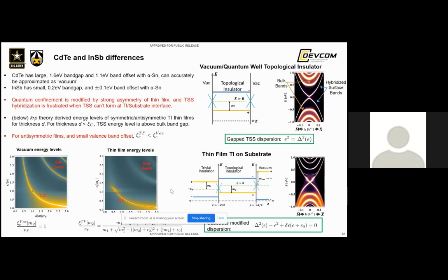Good question. We have thought about that. It's just experimentally very difficult to realize. Alpha tin is quite tricky to grow or to deposit on most materials. It doesn't like too much variation from its lattice constant, so substrates that have a lattice constant that's much different from its own are a problem. And so that's why most people who have grown MBE alpha tin only grow it primarily on two substrates, indium antimonide and CdTe.